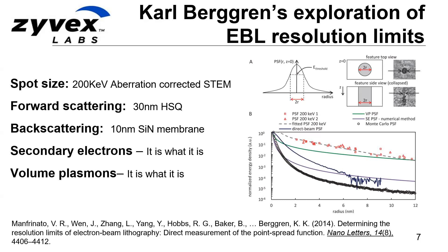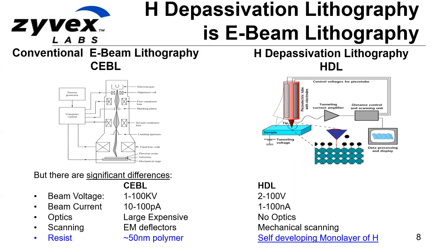Even with a 4-nanometer radius at 10%, by carefully thresholding the resist and developing very carefully, they did achieve roughly a 5-nanometer feature — at least in the narrow direction, a little bigger in the other direction. You can see quite a bit of line edge roughness in the cross-section TEM image of the exposed HSQ.